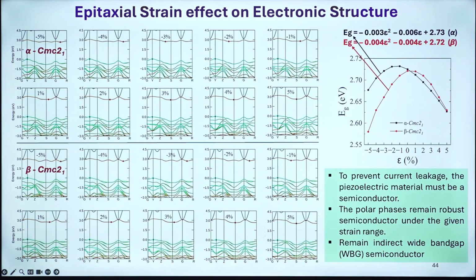Then we also tried to see what happens to the electronic structure if we apply strain. For a material to prevent current leakage, it should remain semiconducting, because when you apply strain or pressure, we do see a semiconductor becoming a metal and eventually it may even become a superconductor. Pressure can tune like strain, strain versus pressure. In this particular case, since the band gap is relatively large, we looked at the electronic structure for all these cases. We could see that for most of the strains, from plus 5 to minus 5, the system remains semiconducting and we don't see a change in the electronic structure of the system.